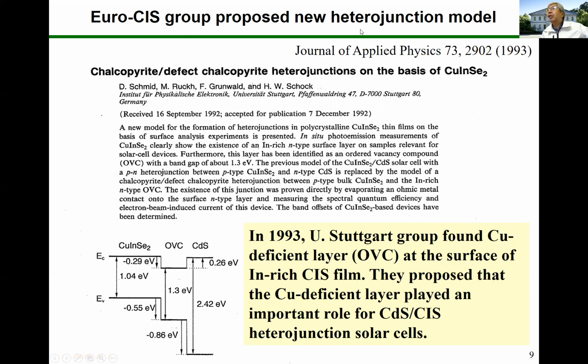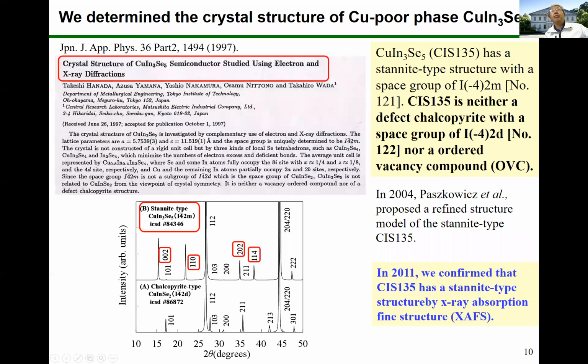The Euro-CIS group proposed a new heterojunction model. In 1993, the University of Stuttgart group, Professor Schock's group, found a Cu-deficient layer at the surface of indium-rich CIS film. They proposed that the Cu-deficient layer played an important role for CdS-CIS heterojunction solar cells. We determined the crystal structure of the Cu-poor phase. CuIn3Se5, CIS-135, has the stannite type structure with the space group I-42m. CIS-135 is neither a defect chalcopyrite with the space group I-4 2d nor an ordered vacancy compound.